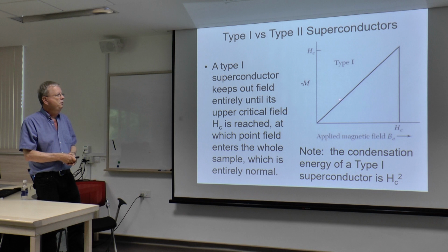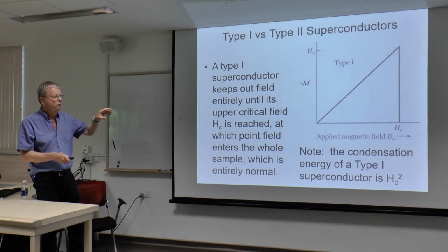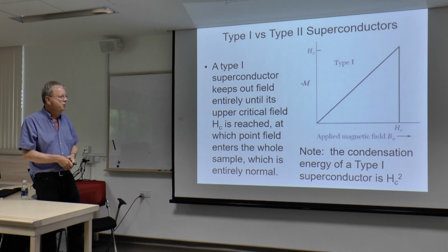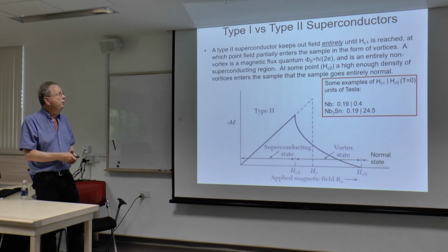And you get flux pinning in both kinds of superconductor. And for those of you who like to study thermodynamics, the condensation energy of a superconductor, the difference between the free energies in the normal and the superconducting state, is the critical field in a type 1 superconductor squared divided by 8 pi. So that's actually a useful piece of information to know if you're worried about energetics.